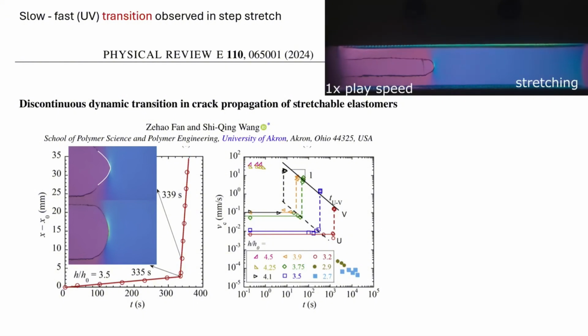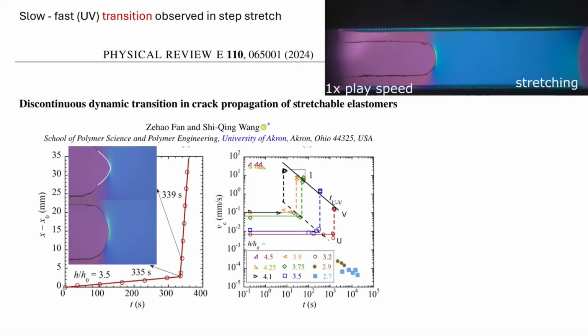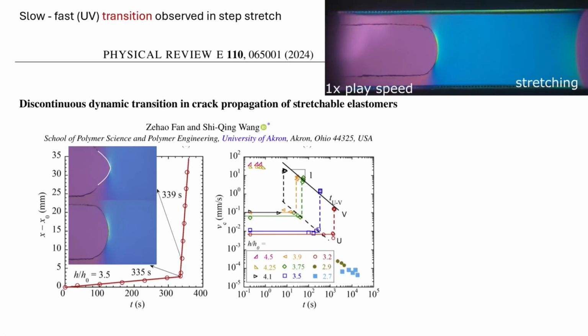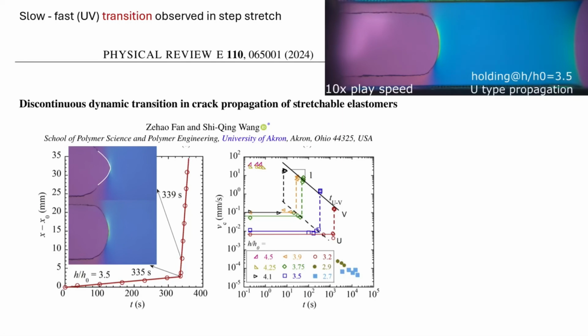So this is one of the very curious ones. We applied our theory and understanding to anticipate this phenomenon, which, by the way, is well known in the literature. It's a fascinating phenomenon. I know Jun Su in the back is fascinated by this. What do you do? With the notch, you stretch it to a certain level and hold. You see the thing slowly propagate. It could wait for an hour, it could wait for 10 minutes, it could wait for 3 seconds.